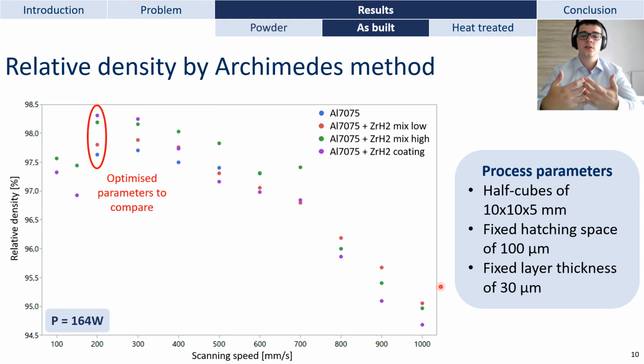So we'll only analyze this low power value for this presentation, and we can see that there is an optimum in the density just above 98% for the high content zirconium mix and the plasma coated powder, while it is just below 98% for the 7075 and for the low zirconium content powder mix. The relatively low relative density is due to the evaporation of zinc and magnesium during the LPBF process, and also due to the hydrogen released by the zirconium hydride particles during the process. So during the rest of the presentation, we will only analyze samples with these optimized parameters, which are a power of 164 watts and a scanning speed of 200 millimeters per second.